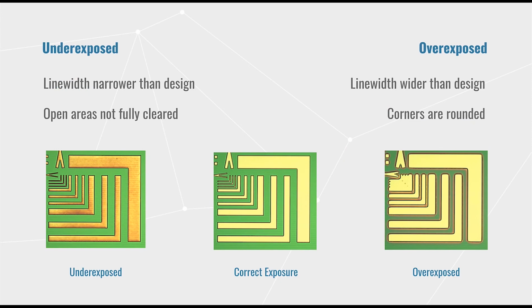During dose testing, you want to find a dose range that will work for your sample. There are certain things to look for that will tell you if your sample is underexposed, good, or overexposed. An underexposed sample will have areas that have not fully cleared, and the design dimensions will be smaller than desired. An overexposed sample will appear blown out, the design dimensions will be larger than desired, and the corners will be rounded. A correct exposure has sharp lines, the right design dimensions, and fully cleared open areas.